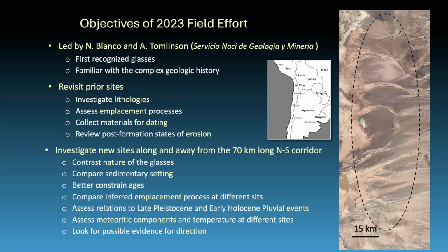And that appeared at the time to be the most probable. But because now they found glass fields that are significantly displaced laterally from that ground track, we can't figure out a physical mechanism by which objects can be accelerated laterally. It's really hard to do because if it's coming in at greater than escape velocity, which it has to be, 11 kilometers per second, you can calculate what the lateral velocity would have to be to give it significantly displaced laterally by the time it hits the ground. That's a very high velocity. It's really hard to get those kinds of lateral accelerations.